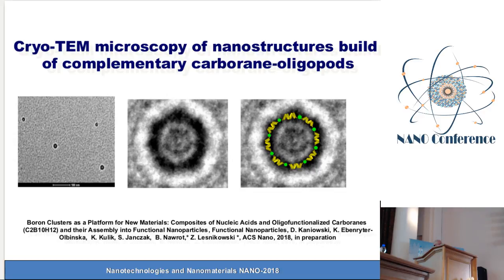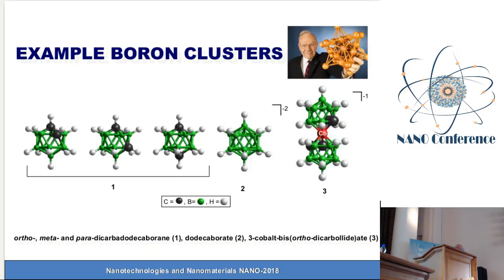It may be strange for you that you can see that boron atoms as well as carbon atoms are 6 coordinated, and this may adapt to the oxidation state or valency of the boron atoms. But these links which you can see here are not real chemical links. They are actually a coordination between the connected atoms. What is even more interesting is that this type of molecule, and it is a property of boron clusters in general, due to the distribution of the charge within the whole molecule, is aromatic in 3 dimensions. They are aromatic in 3 dimensions.